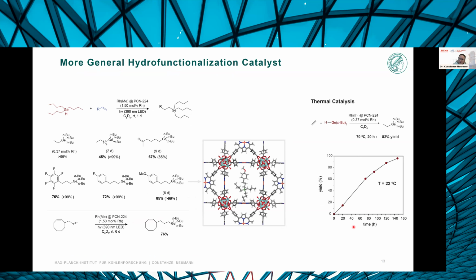And to see if this is something that is essentially restricted to the hydrosilylation reaction, or if this is a more general platform that allows these metalloradicals to engage in catalysis, we also looked at hydrogermylation, which is a less investigated synthetic reaction compared to hydrosilylation. And we found that that can also proceed effectively with the MOF system.